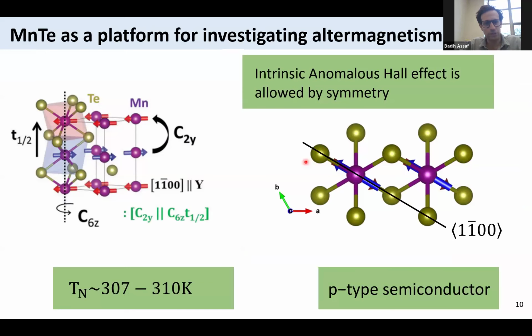Now, maybe the prototypical material to study, and the one that's probably the most interesting from a fundamental point of view, is manganese telluride. I'm showing its crystal structure here. In its alpha phase, it has this hexagonal structure where the in-plane magnetization points along the 1 bar 0 0 direction, and it's ferromagnetic within one layer. But then the interlayer coupling is antiferromagnetic and leads to a vanishingly small magnetization. Now, you cannot map one sublattice to the other using inversion or translation. So there are symmetry arguments that are accepted now that make this material an altermagnet.